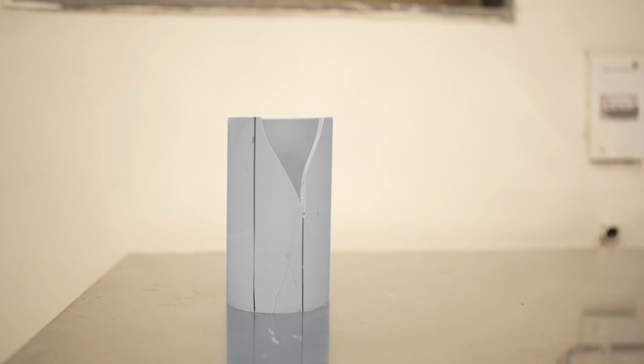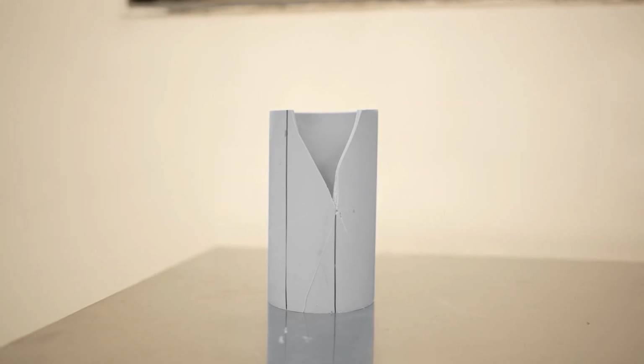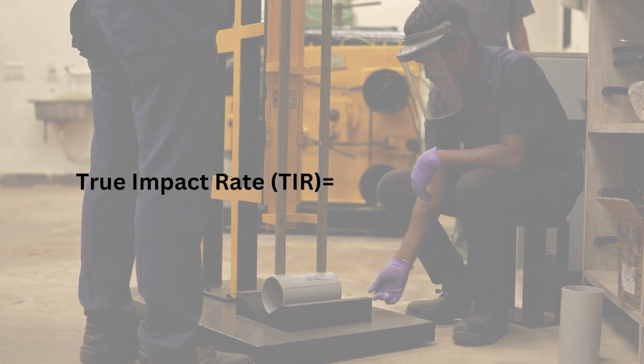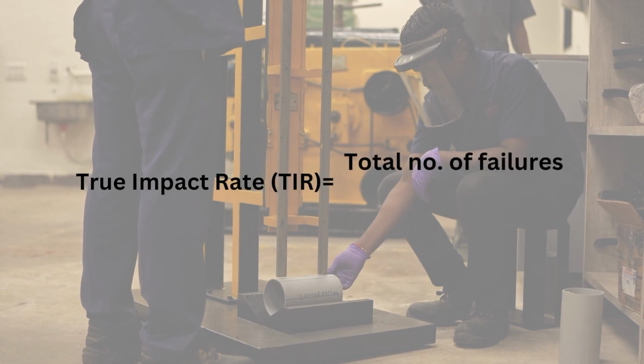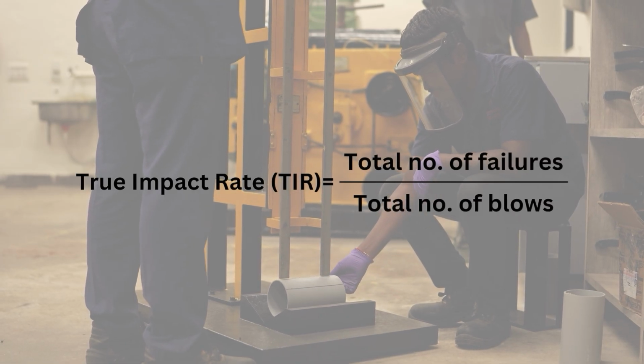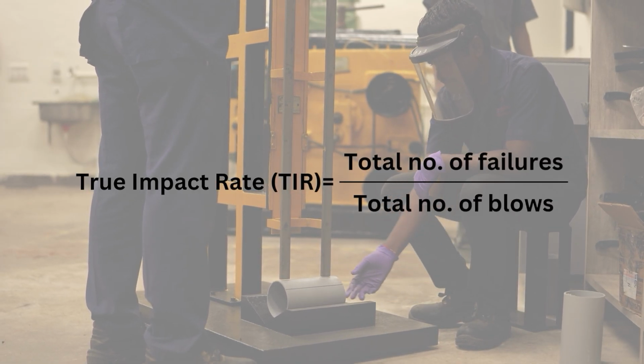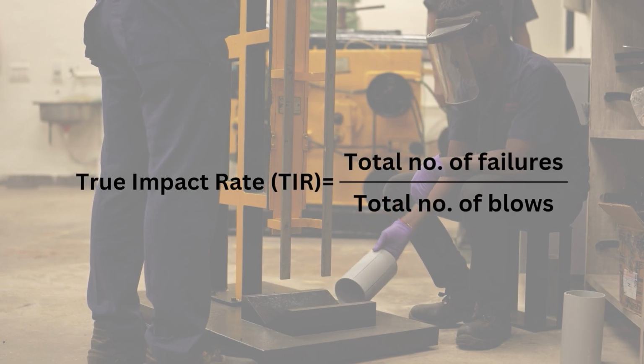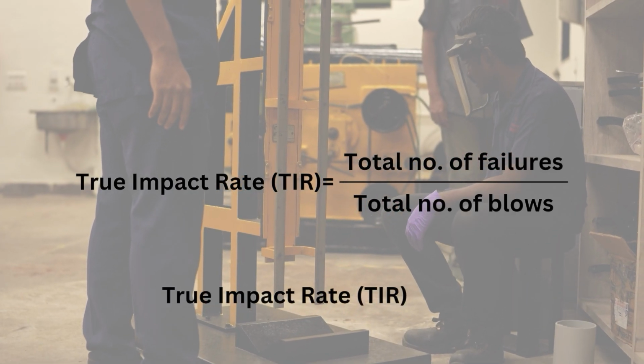Specimens are inspected for cracks or failures after each impact. True impact rate is calculated as the total number of failures divided by the total number of blows as a percentage after the whole batch had been tested. The TIR should not be more than 10%. The next test is the tensile test.